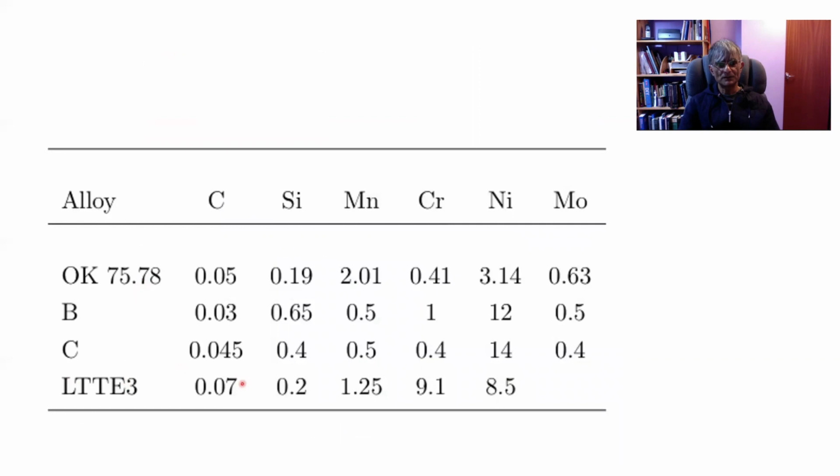So here's a series of welding alloys with very low carbon concentration. This is a commercial alloy, which doesn't actually transform at a low temperature. It's there because we want to do a comparison against alloys here, which do transform at a low temperature because they contain substantial amounts of nickel, for example, or chromium. And they should all give us a martensitic structure. Now, Albury and Jones did their experiment using this constrained tensile specimen, which was a beautiful experiment.